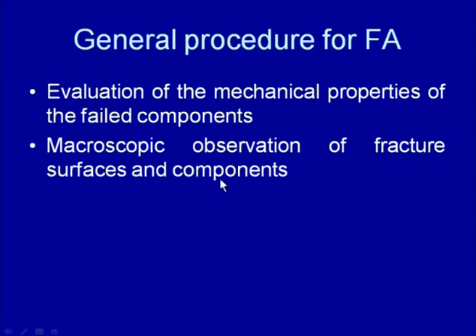very useful information about the stress state in which the failure of the component has taken place, means whether it was under plane stress conditions or plane strain conditions. So the fracture surface macroscopic observation of the failed component will indicate the stress state under which failure has taken place. Then it will show the location from where fracture has taken place, whether it was from the heat affected zone, the weld zone, or the base material in case of weld joints, and at the same time it will show whether the fracture location was close to the toe of the weld or at a location where there was a sharp stress raiser like a hole or the keyway in the mechanical component.